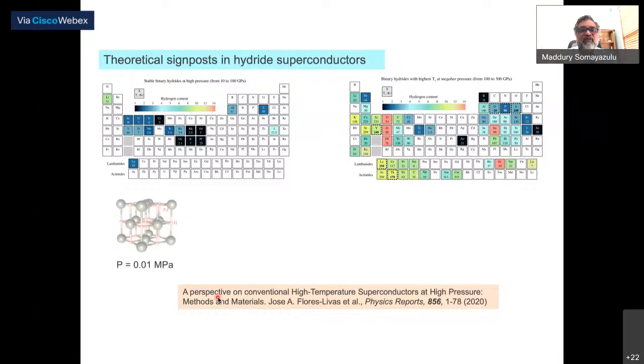What they do find is that at very low pressures, for example, we all know palladium hydride exists. What is the motif for that? You just have one hydrogen per palladium, okay? And the transition temperature in this is as low as 10 or 11 Kelvin, although there have been very recent reports of high transition temperature in palladium hydride of the order of about 30 Kelvin. It's a controversial paper, but again, some of our recent work on palladium hydride under pressure has shown that there is a possibility that you could increase the hydrogen concentration. I will not go into that at this point, but look at the conventional knowledge we have of palladium hydride, which exists at ambient pressure, which has a very simple cubic structure where you have one hydrogen.